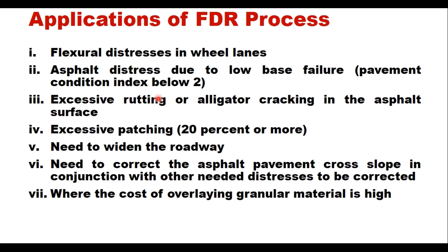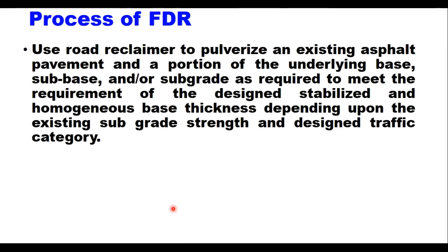FDR is applicable when the pavement condition index goes below 2, when there is excessive rutting or alligator cracking in the asphalt surface, excessive patching more than 20 percent, when there is a need to widen the roadway, or a need to correct the asphalt pavement cross slope in conjunction with other distresses, or when the cost of overlaying or importing new material is very high.